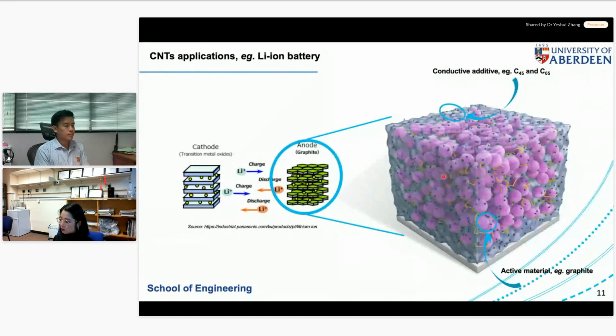So this is a macro structure. Of course, it's a model structure of this anode side. The pink particles represent the active material, for example, the commercial graphite, and the yellow strips here, that's a binder, and it's more like a glue. We try to connect all of these particles together. And if you look at the small black dots here, that's a conductive additive, which is normally mixed with this electrode material to try to boost its electrical conductivity.